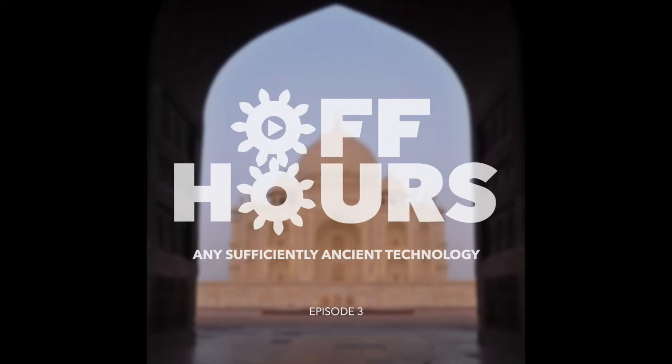And alloys must play some part in that as well. In my case, I tend to be working in silver. It's relatively easy. We're dealing primarily with sterling silver, which is 92.5% pure silver and 7.5% copper. Sterling silver has been a standard since the 11th century, and it just so happens that it's a very nice alloy of silver. But I also tend to work in argentium silver. And argentium is similar to sterling. It has an extra percent of fine silver in there, so it's 93.5%.